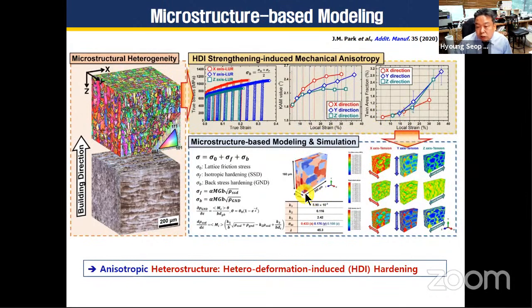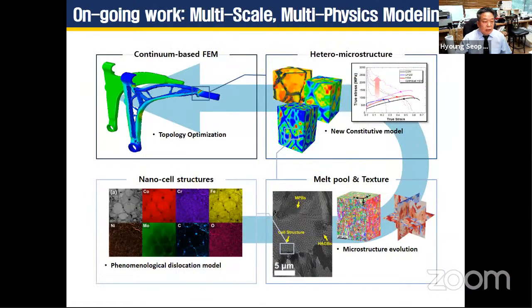We also consider this crystal plasticity, but we found that this macroscopic anisotropy is the source of this mechanical property anisotropy. Now we are working on multi-scale and multi-physics modeling for optimized topology architecturing, macroscopic architecturing, and microstructure and properties. This is the macroscopic topology optimization, this is the mesoscopic heterostructure modeling, and microscopic microstructure evolution and crystal plasticity model, and this nanoscale, and nanoscopic molecular dynamics and phenomenological dislocation kinetics modeling are being done. This is multi-scale and multi-physics modeling.